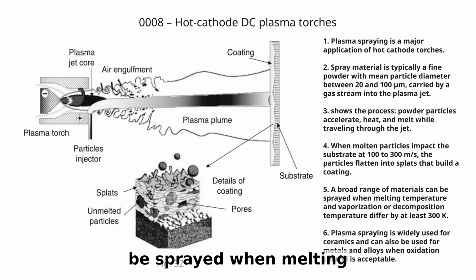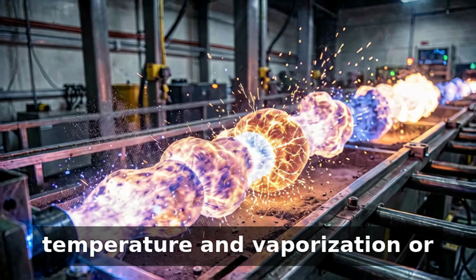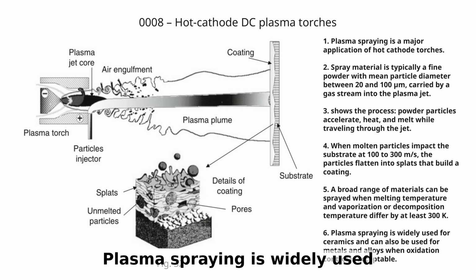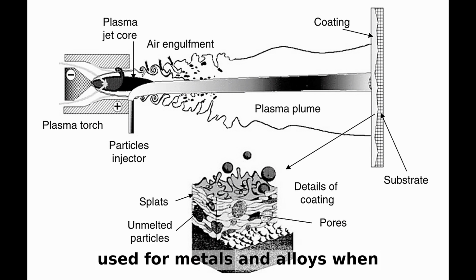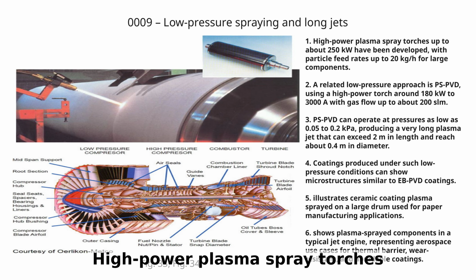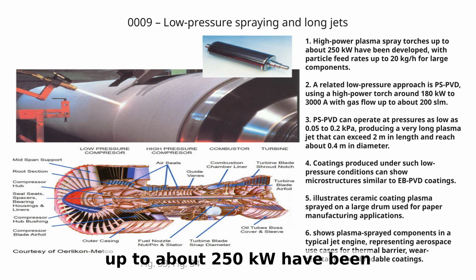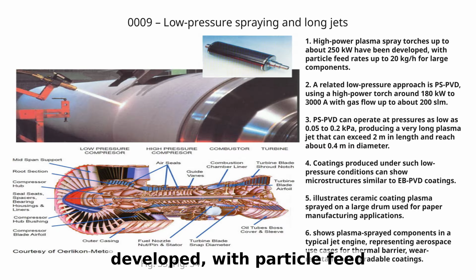A broad range of materials can be sprayed when melting temperature and vaporization or decomposition temperature differ by at least 300 Kelvin. Plasma spraying is widely used for ceramics and can also be used for metals and alloys when oxidation control is acceptable. High-power plasma spray torches up to about 250 kilowatts have been developed, with particle feed rates up to 20 kilograms per hour for large components.